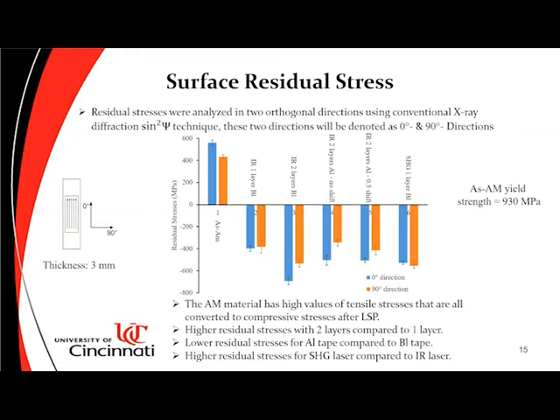When it comes to laser shock peening, residual stresses are a key factor in enhancing the material properties, especially in fatigue. Compressive residual stresses counteract the applied tensile stresses, reducing the net stress experienced by the material, delaying crack initiation, and also decreasing the crack propagation rates.